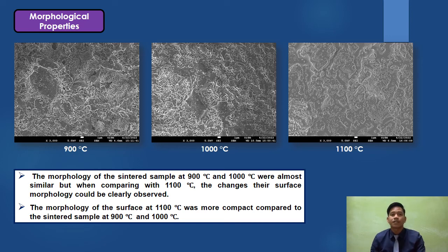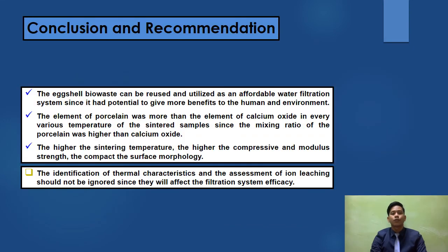The compressive strength was affected by the compactness of the sample's surface. The more compact the surface, the higher the compressive strength. This could be one reason which explains that the compressive strength of sintered samples at 1100 degrees Celsius is the highest among the others. In conclusion, the eggshell biowaste can be reused and utilized as an affordable water filtration system since it has potential to give more benefits to humans and the environment.